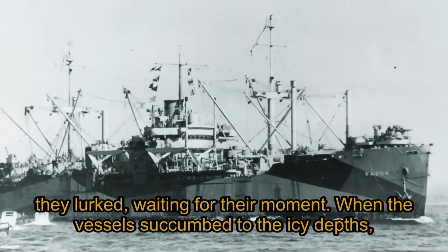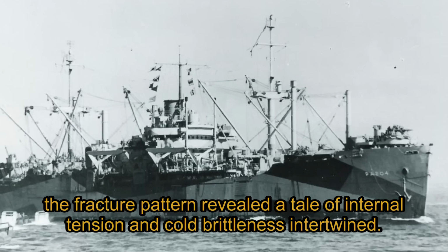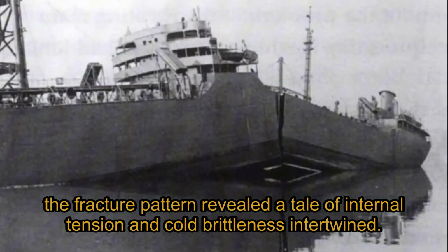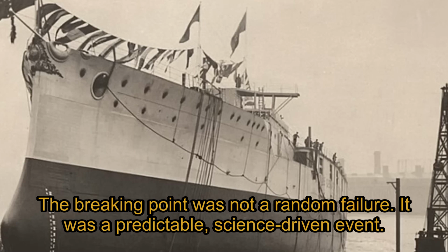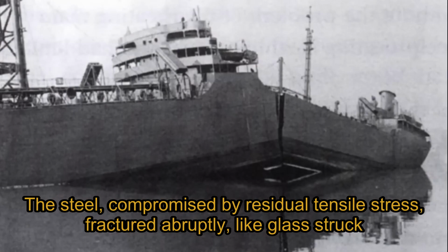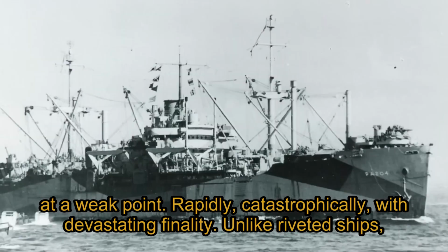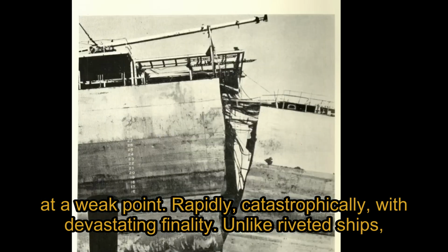When the vessel succumbed to the icy depths, the fracture pattern revealed a tale of internal tension and cold brittleness intertwined. The breaking point was not a random failure. It was a predictable, science-driven event. The steel, compromised by residual tensile stress, fractured abruptly, like glass struck at a weak point. Rapidly, catastrophically, with devastating finality.